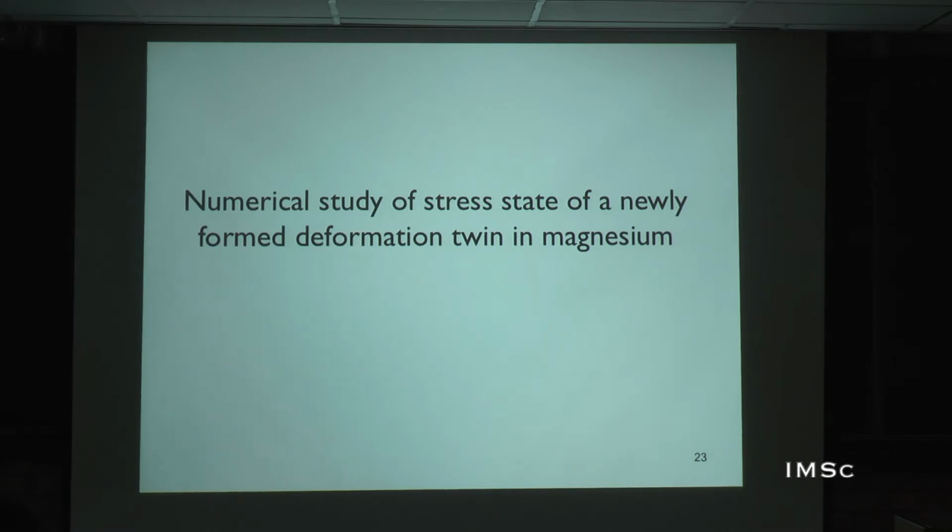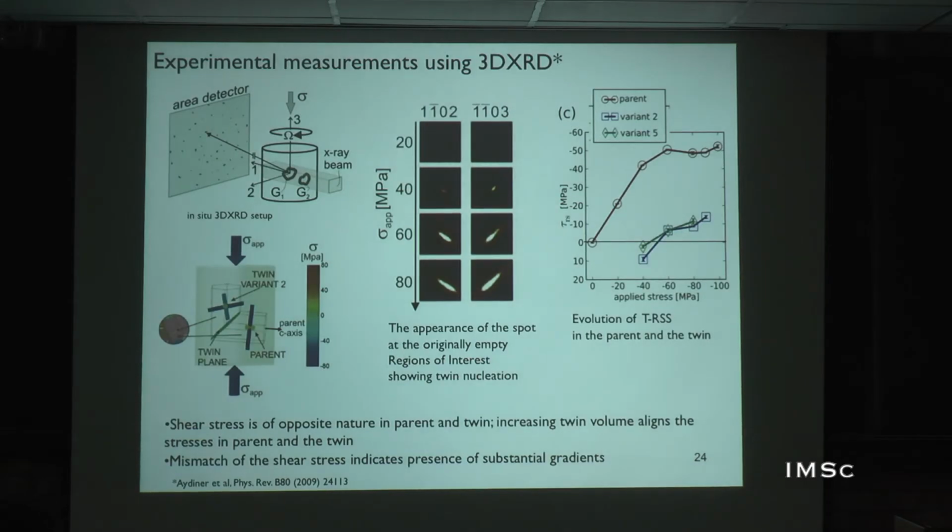I like this particular work, so I am going to quickly explain this. There was an experiment done in 2007, I think, and published after 2 years of analysis. It was the first time an experiment was done where you monitor a grain while it is being deformed in situ. You send very high energy X-rays and you know the grain in its nascent state, and as you deform it, you are able to measure the average stress in the grain because you get the lattice diffraction patterns.